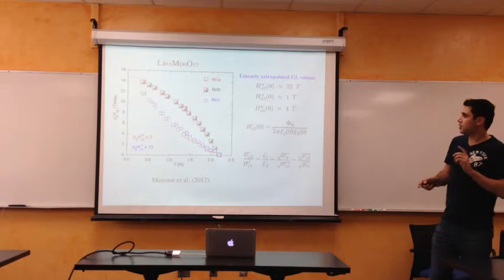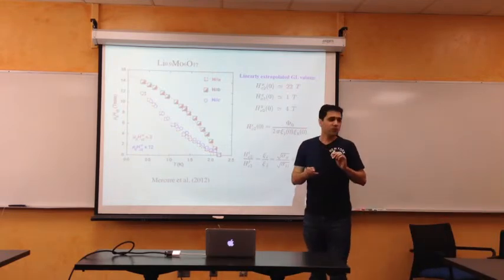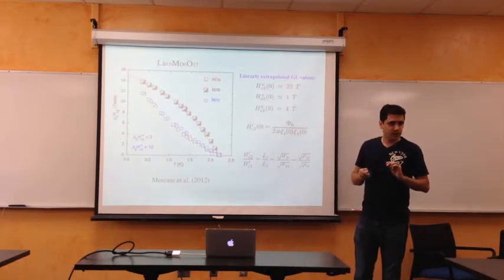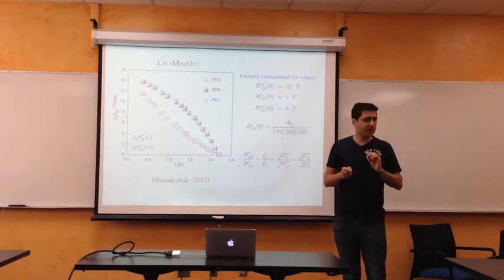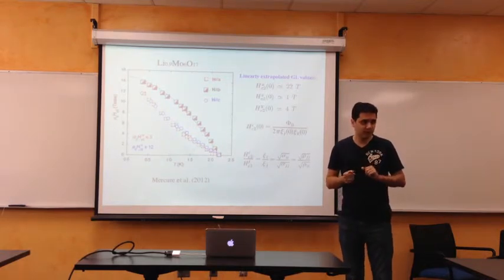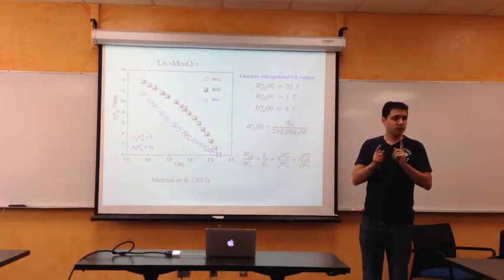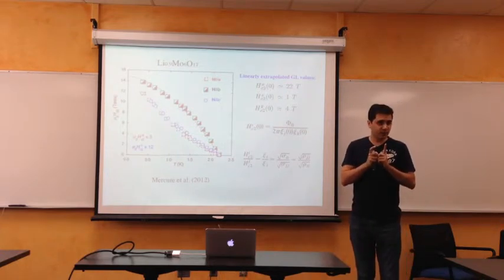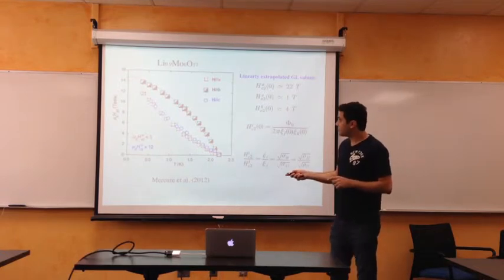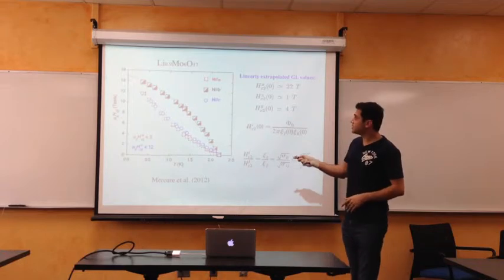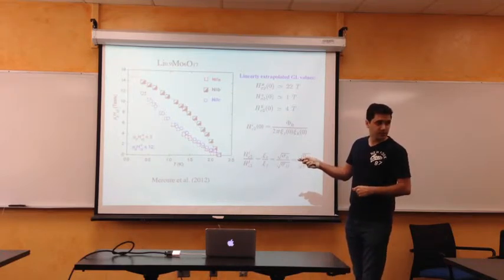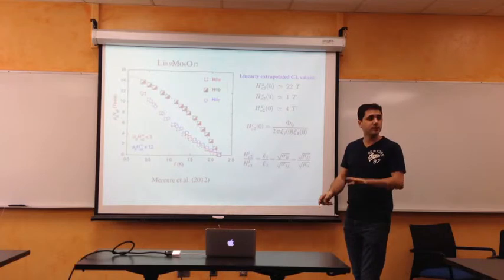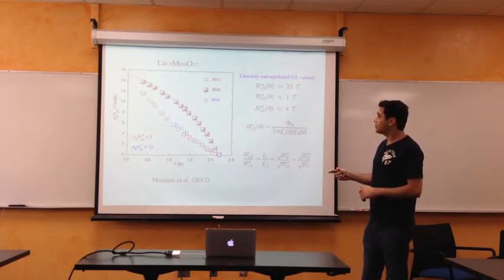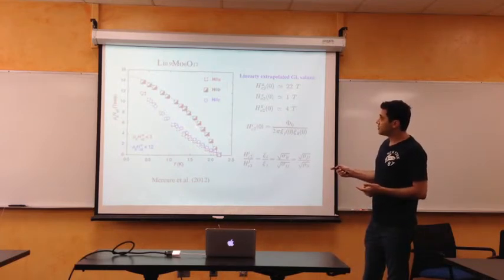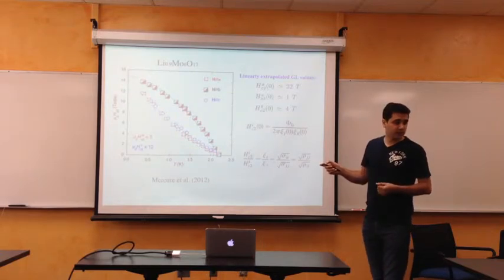Because what is... I'm saying that if it was a singlet superconductor, when you reach a value of about 3 Tesla in externally applied magnetic field, the spins would align. It would be energetically unfavorable, because of the Zeeman splitting, to stay in a superconducting state. That would happen at 3 Tesla, so we wouldn't see this high saturation limit here. Superconductivity would be destroyed much earlier than that. But the fact is that this experimental plot shows that it doesn't do that.